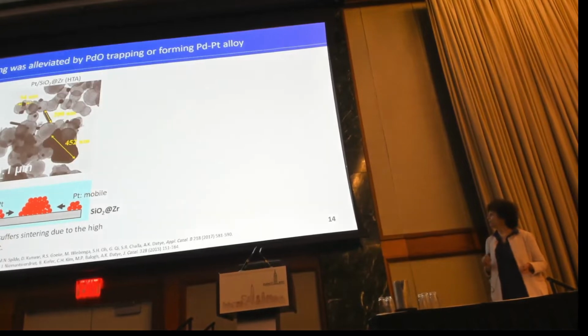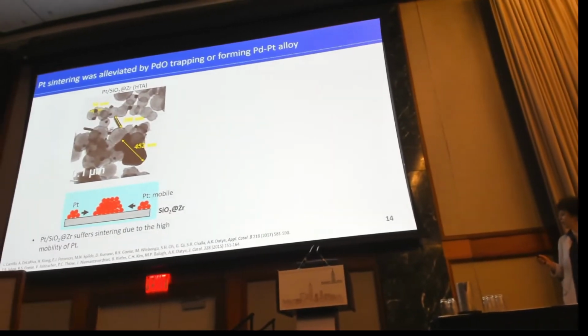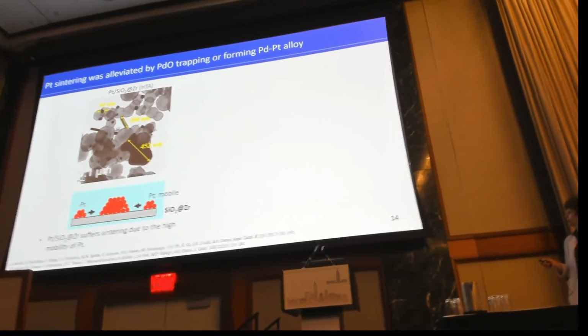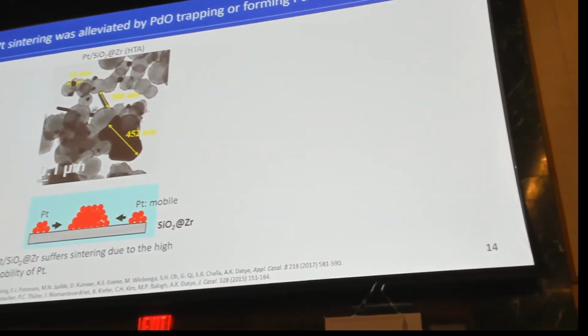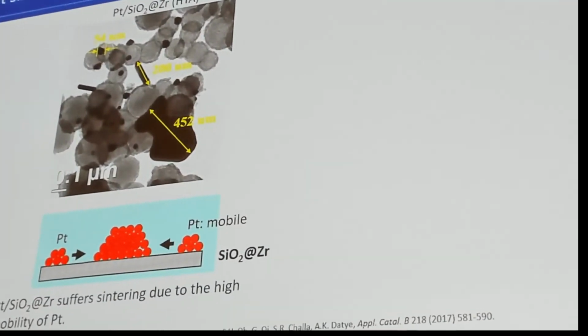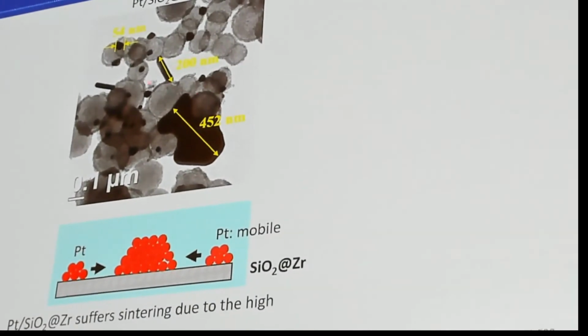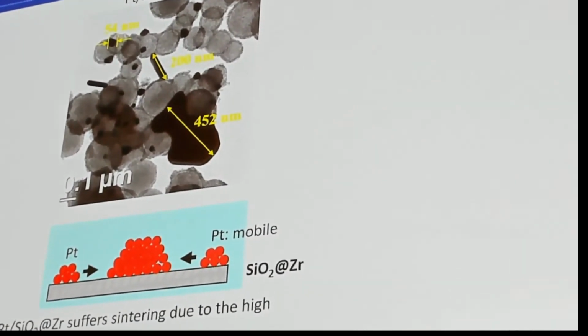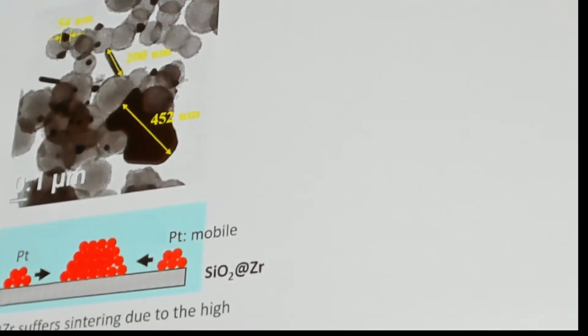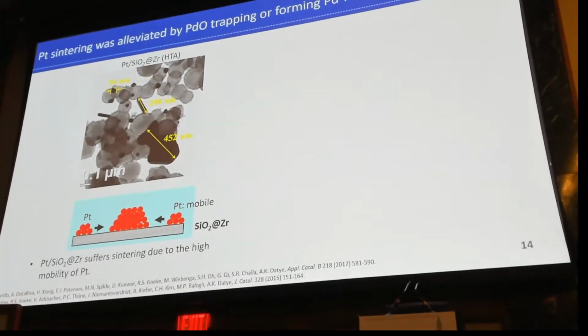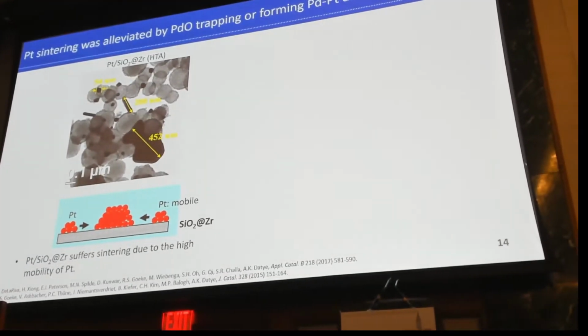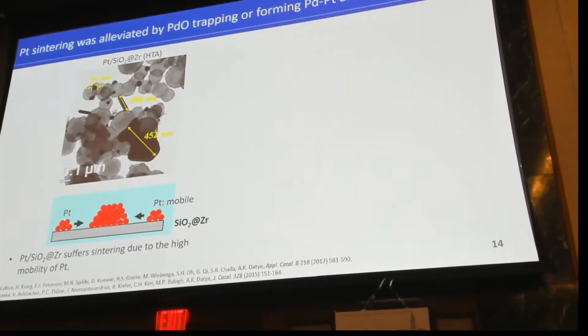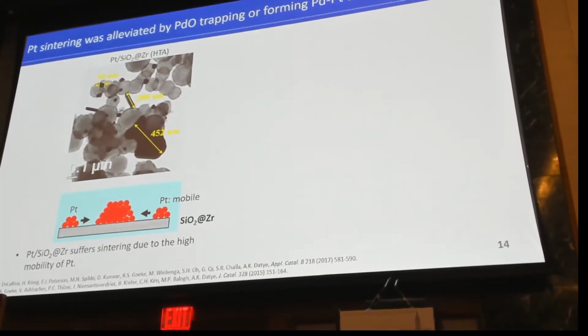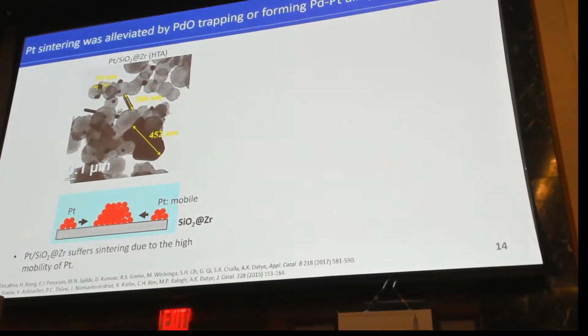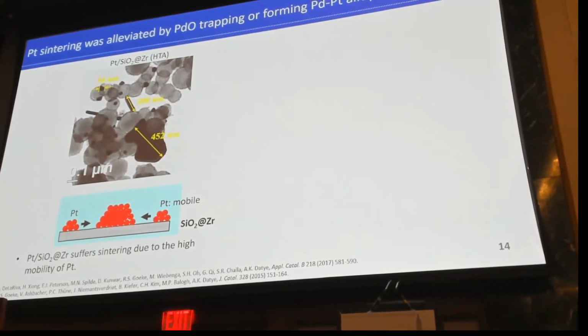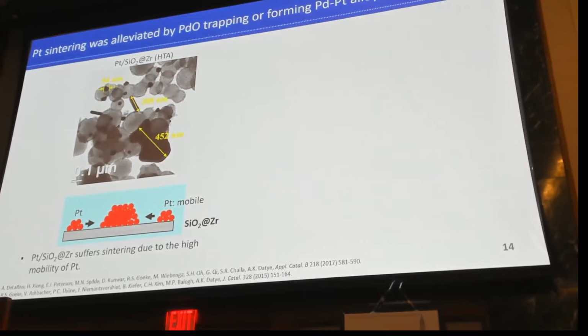And so here you can see a TEM image for the platinum supported on the silica zirconium support after hydrothermal aging. Okay, so platinum severely sinters, as you can see here. It forms these very big platinum particles, close to 450 nanometers. And this is not the only particle that we saw. This is an example, so we saw a couple of them. So what happens with platinum? Platinum is mobile. During hydrothermal aging, it can form these big platinum aggregates. Okay, so this is not desirable.